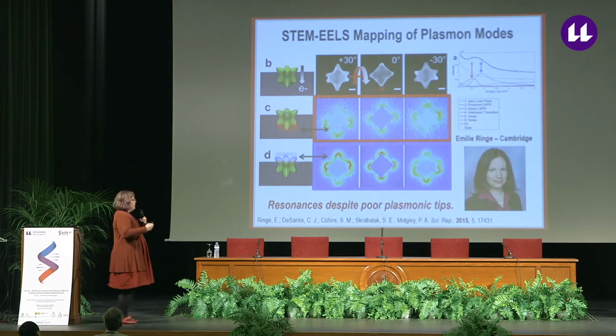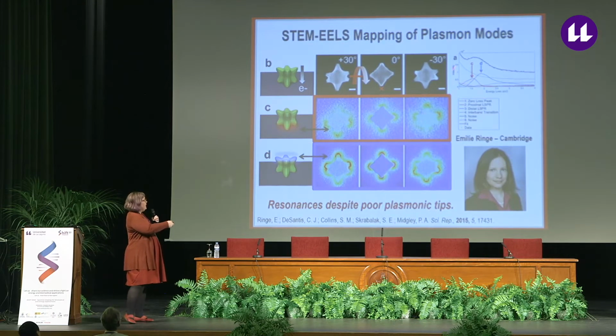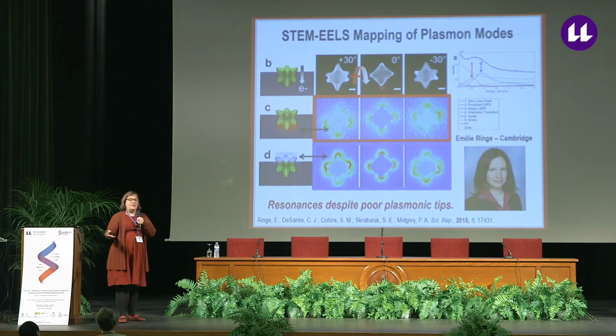But what I was actually most excited about was that when she started to analyze the EELS spectrum, she was able to pull out 2 different resonances. One that is corresponding primarily to the resonance into the high dielectric TEM grid, and one that's associated with a resonance primarily out into the vacuum of the electron microscope. And what this is telling us is that the nanocrystals, even with these plasmonic tips, is sensing changes in its local environment, that it can tell that there's a different refractive index out into the microscope versus on the substrate.